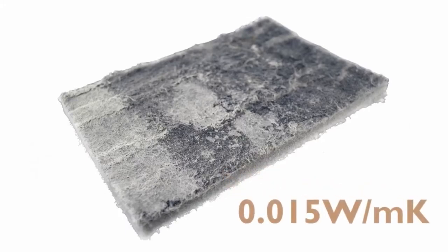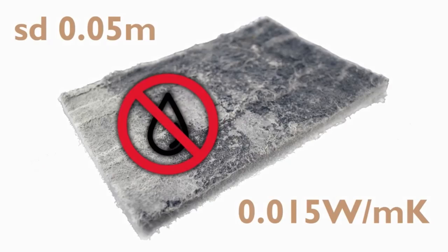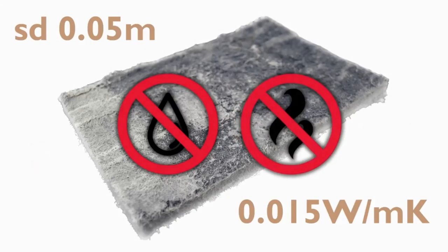The thermal conductivity of 0.015 watts per meter kelvin makes it amongst the best thermal insulations in use today, which combined with its high vapour permeability makes it ideal for refurbishments. SpaceTherm Aerogel is also hydrophobic, meaning it repels liquid water. Because the aerogel insulation blanket contains no blowing agents, it does not release harmful gases into the building over time, nor does its performance degrade, with extensive testing showing no loss of thermal performance over a 50 year period.